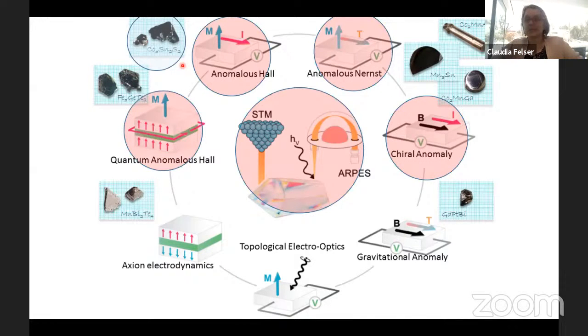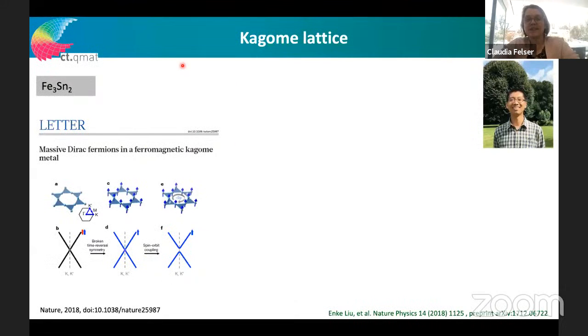This is because this is a quasi two-dimensional material and it's a Kagome lattice. People who are in correlated materials like Kagome lattices, and this area of research started with some very nice work of Joe Checkelsky from MIT, when he proposed that iron-3 tin-2 is a very nice ferromagnetic Kagome metal, which has a Dirac cone because of the symmetry of the crystal in the material. Additionally, nowadays it's also known that in this ferromagnetic Kagome lattice we have not only these crossing points, we also have flat bands, which are even more interesting in the community of correlation.